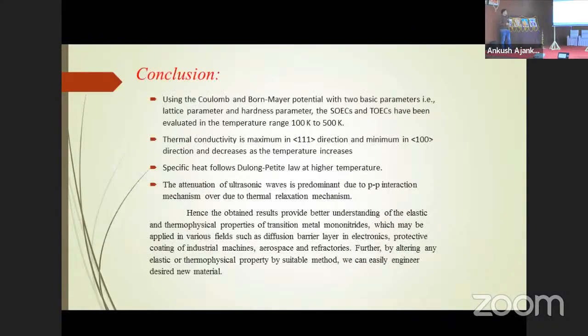And I conclude that using two basic parameters, lattice parameter and hardness parameter, second order and third order elastic constants can be evaluated between 100 Kelvin and 500 Kelvin, and thermal conductivity is maximum in the 111 direction. The obtained results provide a better understanding of the elastic and thermophysical properties of transition metal mononitrides.